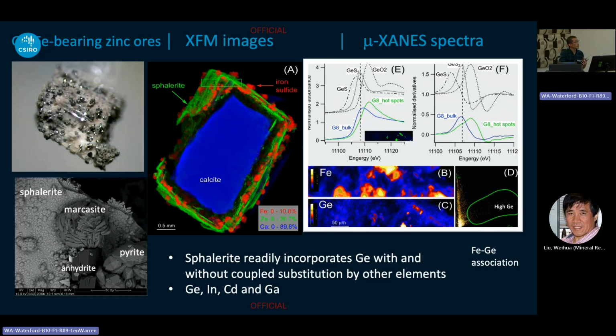And for their association, the example here is germanium and iron. There's no clear association between germanium and iron. What it says is you don't necessarily need iron to make germanium incorporate in sphalerite. It is there because the structure of sphalerite helps germanium incorporation into the lattice. And you can worry about coupled substitution or solid solutions, whatever. It is there because sphalerite favors germanium incorporation. So those are the key messages from the experiments.